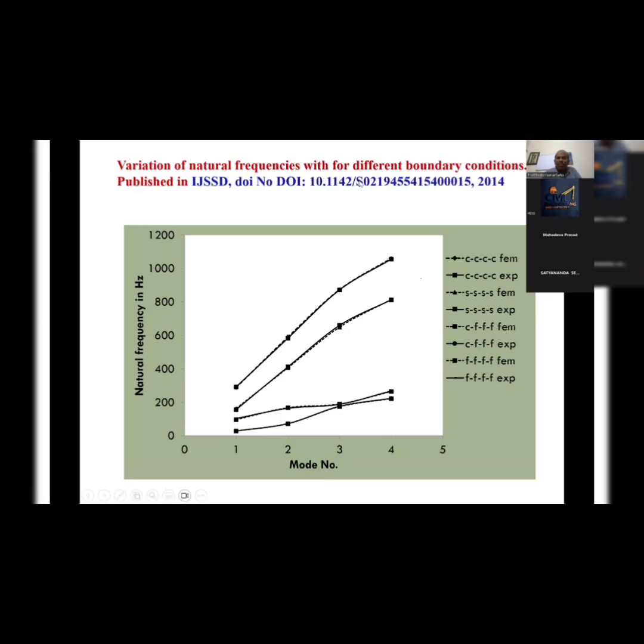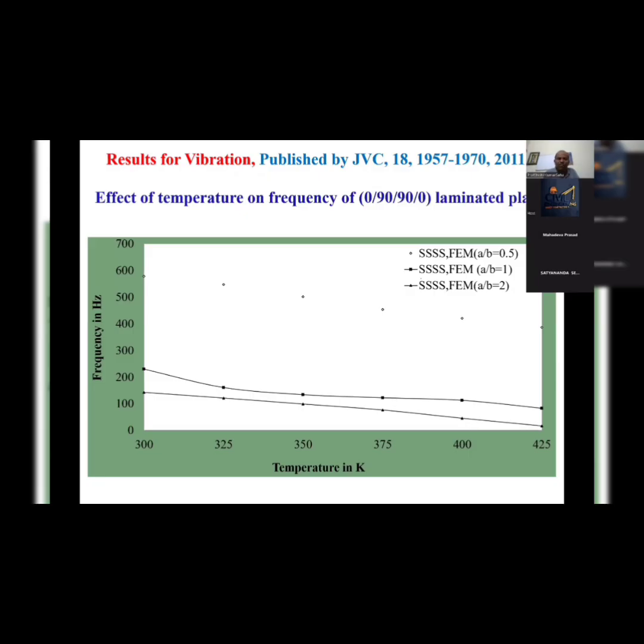Variation of natural frequency for different boundary conditions. The top one is the clamped condition, which shows the highest, then simply supported, then free, then cantilever is the lowest frequency. Fully clamped shows the highest because of restraint at the edges. We have done experiment as well as the computational values.